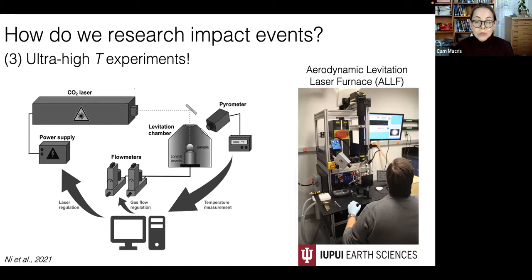We can reproduce the extreme temperatures associated with impact melting and impact plumes in a device called an aerodynamic levitation laser furnace. On the right is a photograph of this apparatus in my lab. And on the left is a schematic of its parts and how they work together. In this apparatus, a small spherical sample is levitated on top of a flow of gas that comes from below out of a specially shaped nozzle. It's heated from above with a CO2 laser, and the temperature is measured with a pyrometer.